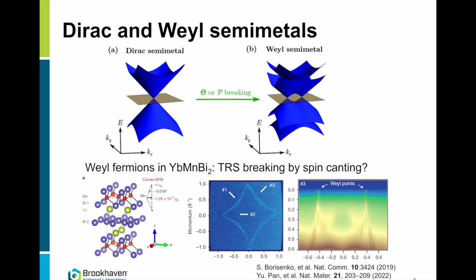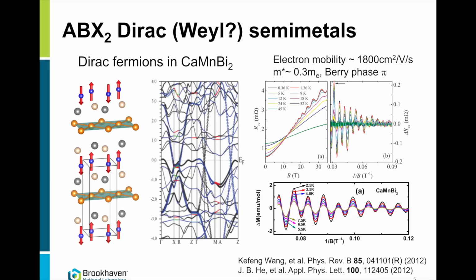And of course, it's unverifiable by neutron scattering because we can measure a few degrees, but we cannot measure 0.02 degrees. And of course, this is a bulk measurement. So you have all sorts of little ferromagnetic mixtures, and you measure it and you assign it to a canting. So it's not serious.